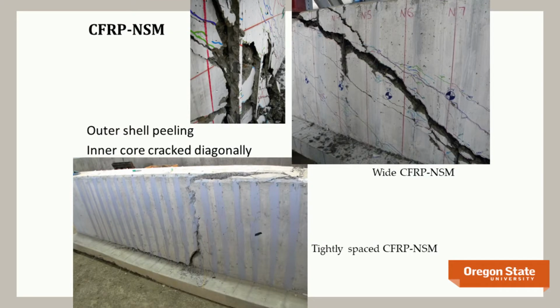And we've done work with this with carbon fiber, and you find that if you have widely spaced carbon fiber, you end up with, so you can see this is a pre-cured bar that's kind of ripped out of the groove of the epoxy groove. So the bar's still intact, but we've failed the bond. If we have really tight bar spacing, essentially what we do is we rip off the cover.